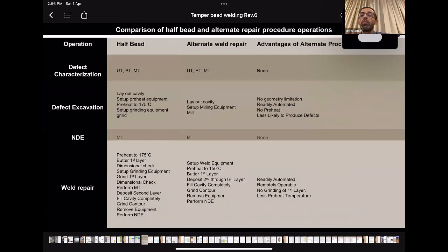This is a comparison between half bead and alternate repair procedure operation. As we can see, the advantages of the alternate procedure over the half bead procedure: no geometry limitation, readily automated. Of course, the technique used in this method is automatic GTAW or TIG welding, no preheat, and less likely to produce defects. So it is better than SMAW, and remotely operated, no grinding of the first layer, and less preheat temperature.